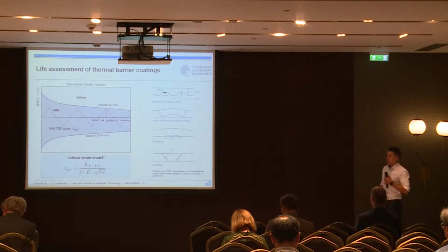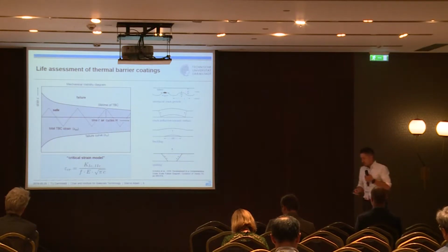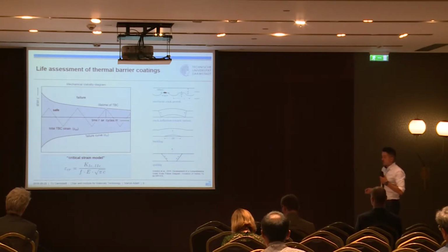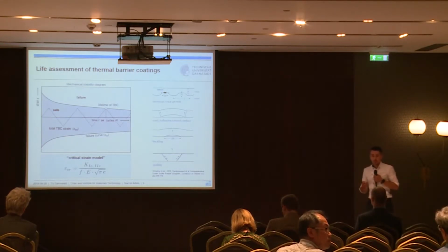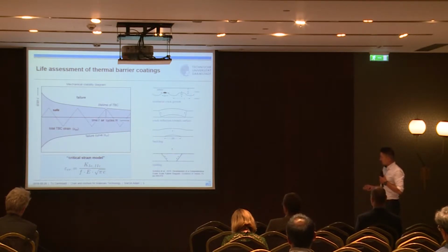In thermal barrier coatings, you will often find very different failure mechanisms. For example, an interface crack, or some kind of buckling or spallation. If you want to study your thermal barrier coating and assess its lifetime, you have to take all these failure mechanisms into account. In the past, researchers developed several lifetime models to do that. In the literature, you will find empirical, phenomenological models, and models based on TGO growth and so on. But in the case of double-layer thermal barrier coatings, they all won't work.